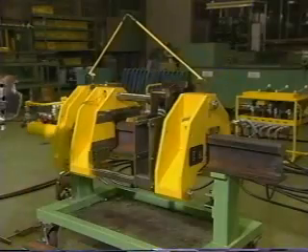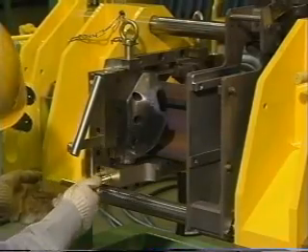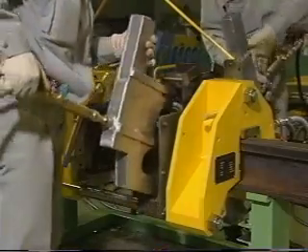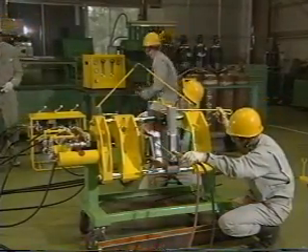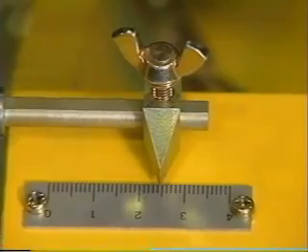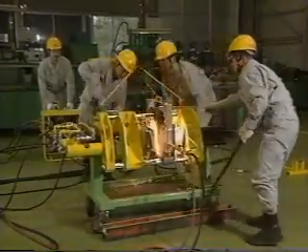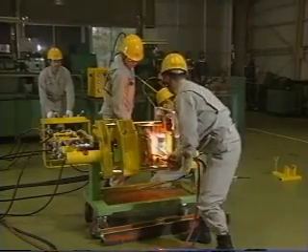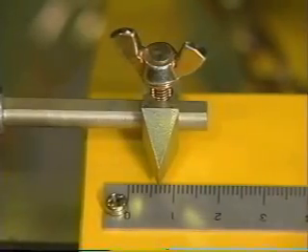After setting the trimmer on the rail, the burner is set. Ignite the gas with the burner away from the end faces. Make an adjustment so that the flame of the right burner is uniform with that of the left burner. Continue heating and perform pressure welding while the burner is moving along the pressure welding gauge. Perform buckling at 10mm before the prescribed pressure welding gauge. Atoms of the two rails at the contact face are mixed through pressure and heat, and crystals are generated at the bulge where metallic bonding is achieved.